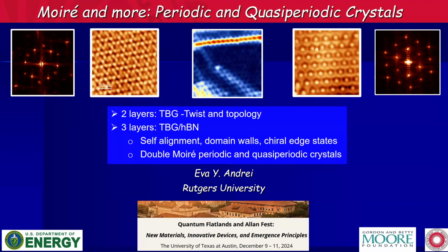So I'm going to start with when you take two atomic crystals and superpose them to create a moire pattern, which is a super period. It turns out that when you look at the density of states of the band structure, this moire pattern actually creates a periodic potential that changes the band structure. And all sorts of interesting things can happen as a function of the twist. In particular, you can get flat bands, Van Hove singularities, correlated states, etc. So I'm going to start with a little bit of a review of that, and then I'm going to move on.